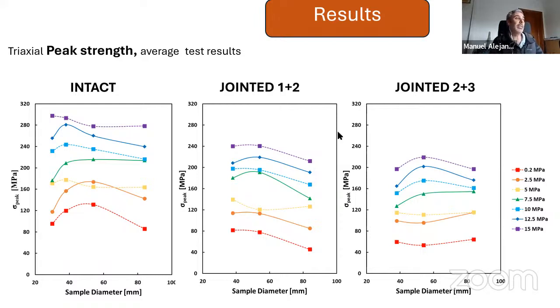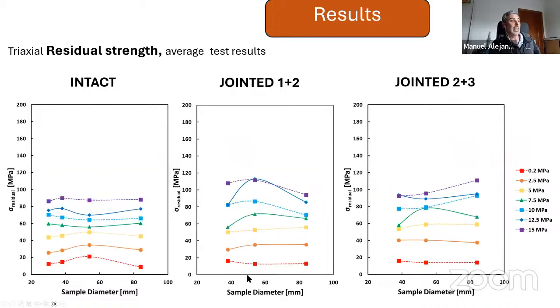And here we can see, in this case for the jointed 1+2 and 2+3, that there is a very little descending trend for the peak strength. Also for the residual strength, we can see that it also increases with increasing confining pressure, and we can see clearly that the residual strength is barely affected by the size of the sample, and it is slightly affected by the level of jointing of the specimen.